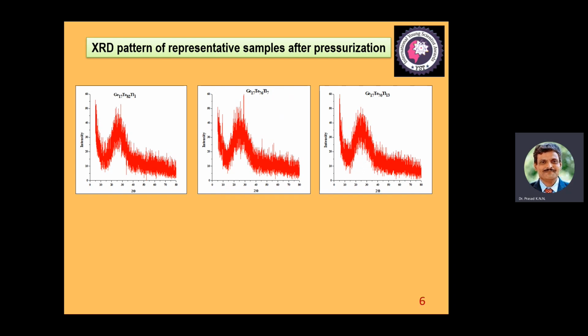Again, to check what might have happened to our samples after being pressurized to a very high pressure, XRD has been taken again, and here are the representative samples of the same material after applying pressure. The XRD patterns of representative samples after pressurization are shown here.